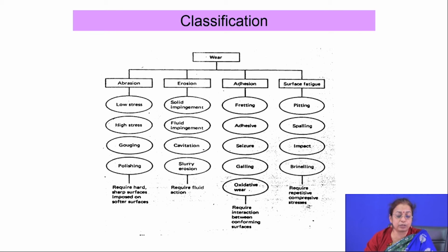For example, in the case of abrasive wear, you do not give any lubricant. You just have the abrasive mating surface, and the component surface, with relative movement between the two surfaces. If it is adhesive wear, then the other mating surface must be of similar composition, based on the actual service condition of the component, so that adhesive joint formation is promoted.